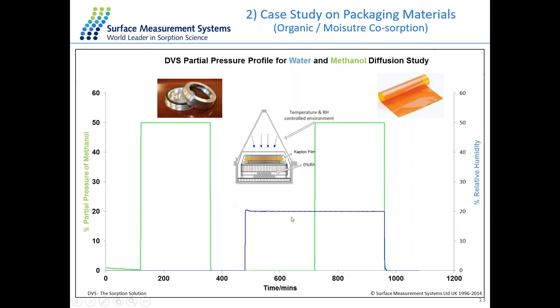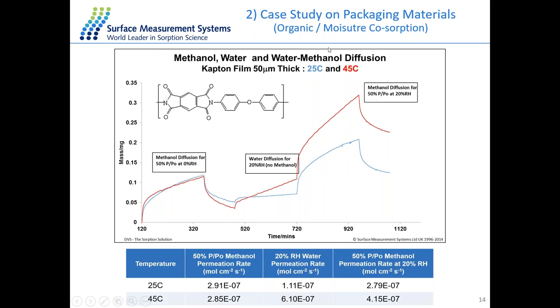So we expose the same sample at different temperatures, and we measure the temperature effect on the diffusion of both water and methanol. Here the blue line is for 25 degrees, and the red line is for 45 degrees. With the equation I showed in the previous slide, you do the fitting of the lines, and then you can calculate the permeation rate at different temperatures and different stages. First, for the methanol only stage, you can see the plots are similar, just overlapping here. And the values at two different temperatures are almost the same as well, which means temperature has very little impact on the methanol diffusion.